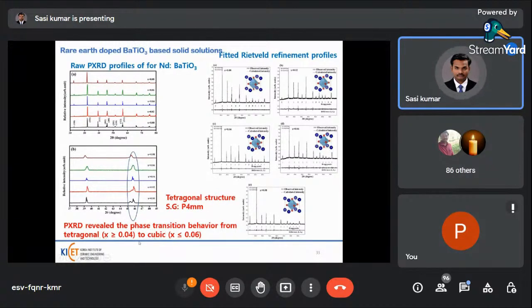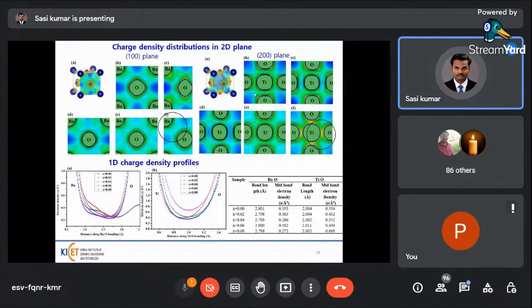A phase transition from tetragonal to cubic is observed in that material, and then Rietveld refinement is also plotted for these compositions. Charge density distribution in two-dimensional plane for the Nd doped barium titanate materials on different planes, 100 plane and 200 plane, is shown here. And then one-dimensional charge density distribution gives the bond length between Ba and O and Ti and O, and then the mid-bond electron density of these compositions.